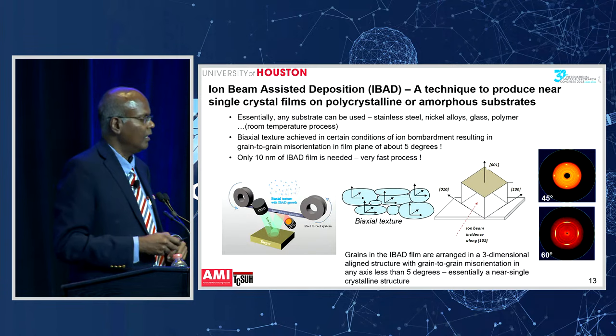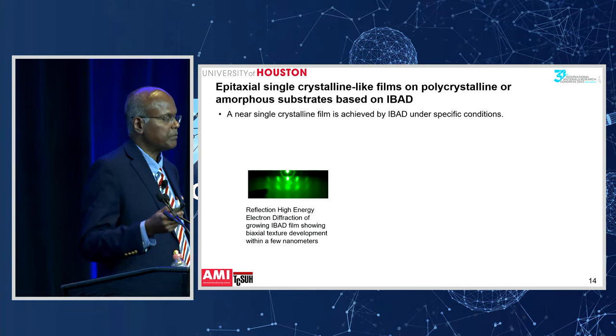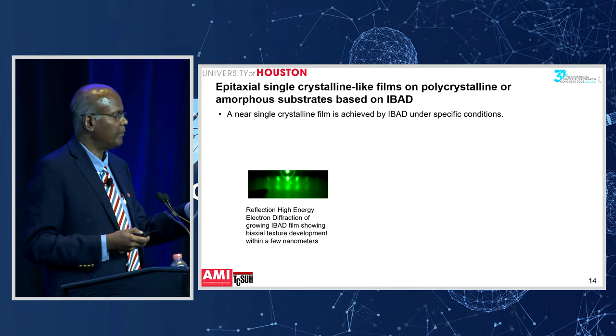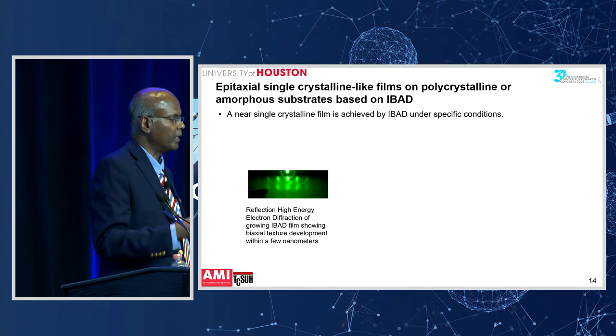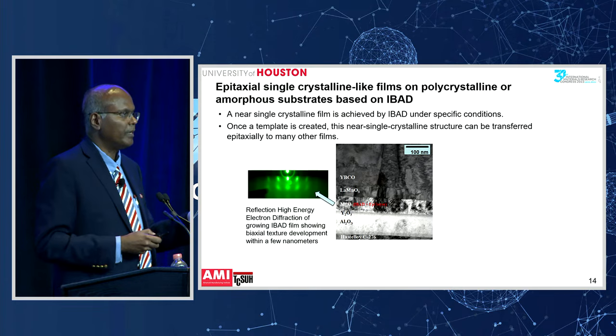So once you have created this IBAD film, now we can actually epitaxially grow many, many types of films on this. By the way, you can monitor the quality of this magnesium oxide IBAD film by reflection high energy electron diffraction, in situ, while you're doing the process. So you can confirm the quality of the film that you're making. And like I said, once you make the IBAD film, then you can grow many films.